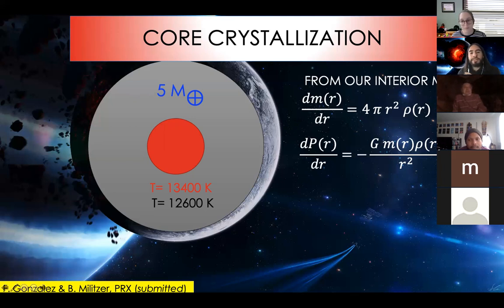So here we basically predict that the lowest melting temperature would be 12,000 Kelvin, 12,600, for the conditions of the core. At the lowest pressure, this would be the melting temperature. So if you have an average temperature that is below that, and some models suggest 6,000 Kelvin, then no part of the core has a temperature that's higher than the melting temperature of iron. So all the possible pressures that you will find there have melting temperatures that are above what any model would suggest. It is still possible that these temperatures can be so high, but actually constraining the temperature inside an exoplanet is very, very difficult. Currently, from what we know, temperatures would never reach such high values.